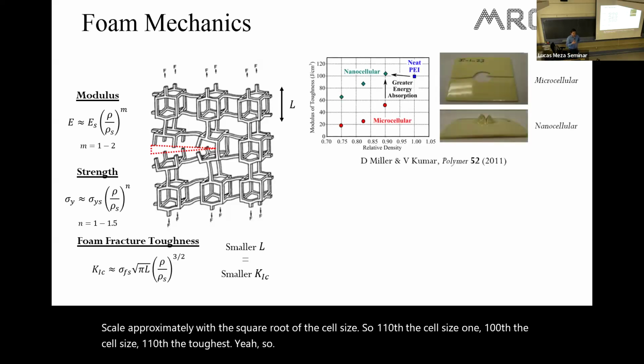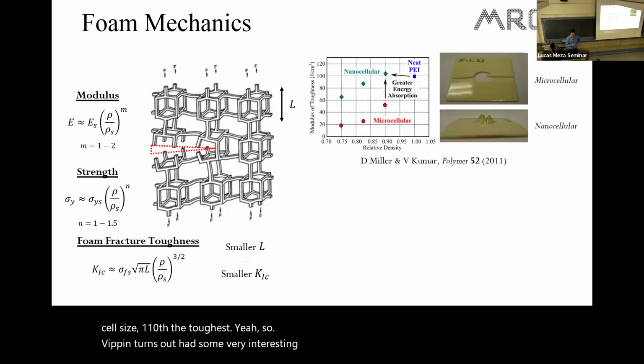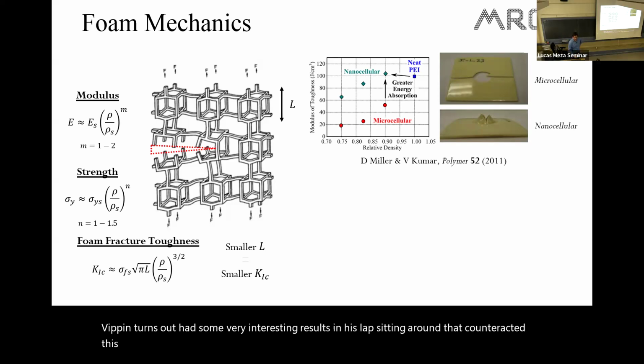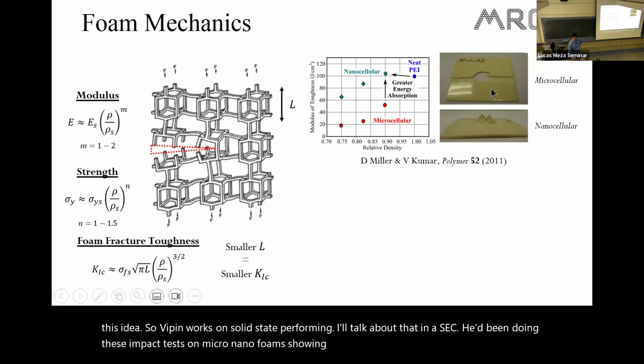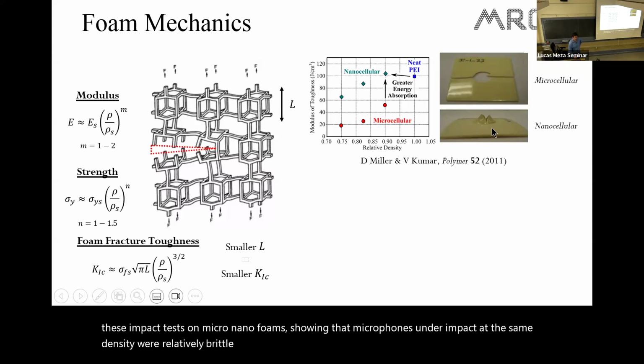Vipin, it turns out, had some very interesting results in his lab sitting around that counteracted this idea. So Vipin works on solid state foaming. I'll talk about that in a sec. He had been doing these impact tests on micro and nanofoams, showing that microfoams under impact at the same density were relatively brittle, but nanofoams were not.